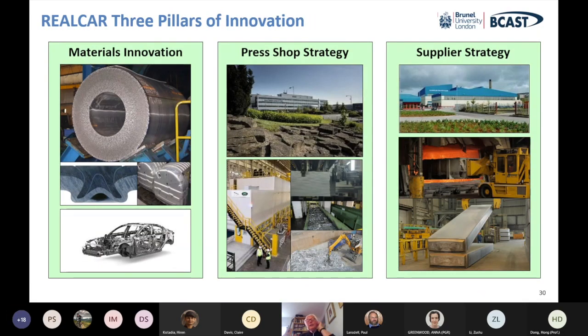And what we did, we looked at how contaminated the press shop scrap could be with iron, and we could still make 5754 sheet that would roll. You can see that one's got some nice edge cracking. That's one where we actually put too much iron in the trial coil, and you can see we've got cracking of the edges, which isn't very nice. If we put any more in, we actually got cracking of the ingots as well.